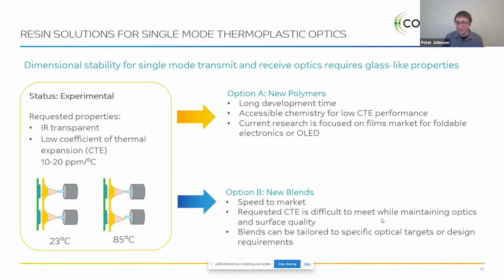The second thing that we get feedback on is single mode optics. So having single mode transmit and receive optics really requires glass-like properties. The requested properties here, of course, are still having that IR transparency, but it's also having this low coefficient of thermal expansion. So when we're talking 10 to 20 parts per million per degree C, it's more that the PCB board or the silicon chip, if this is silicon photonics, will expand by that rate. So the optics themselves also need to align with that coefficient of thermal expansion. And what that can do is it can cause a misalignment if we would just use the standard thermoplastic like Ultem that we currently have.